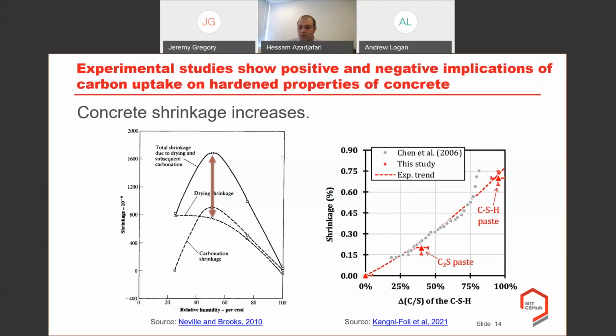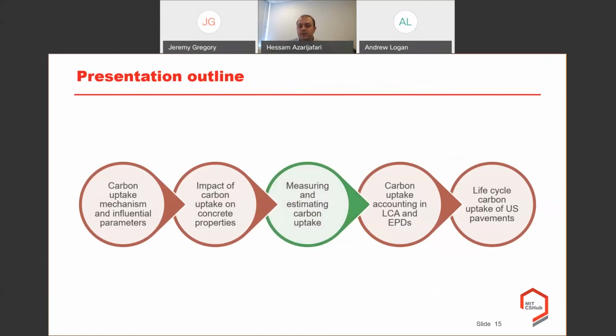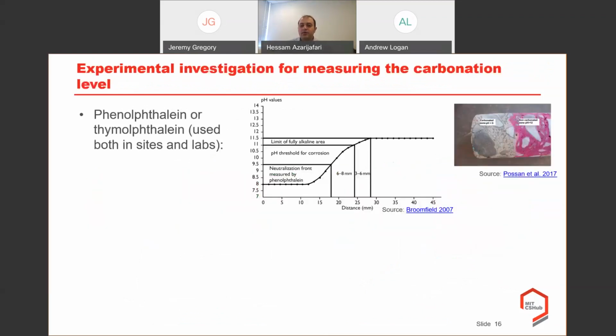So we don't want to go through the details of the chemistry and the calculations, because we just want to know the consequences and the impacts, positive and negative implications of the carbon uptake on the hardened properties of concrete briefly. We will talk also very briefly about the measurement and the estimation of the carbon uptake based on different models. The most conventional method for measuring the carbonation is spraying some pH indicators like phenolphthalein or thymolphthalein, which can be used both in construction sites or in the labs.